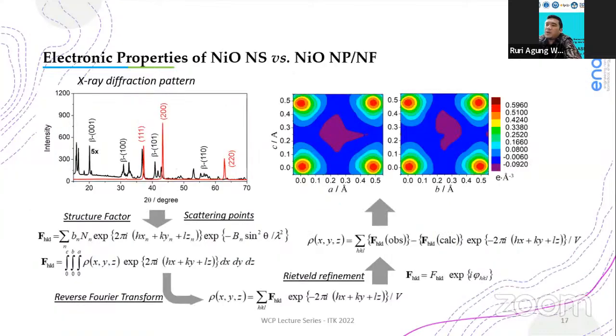And then the structure and electronic properties of nickel oxide are now examined using X-ray diffraction. As an example here, I show the diffraction pattern of nickel hydroxide preforming the nanosheets and the diffraction pattern of nanosheets itself. It is confirmed from the phase matching and refinement that nickel oxide is cubic bunsenite. And to further explore the electronic properties, we have examined the Fourier map derived from the diffraction pattern that is extracted